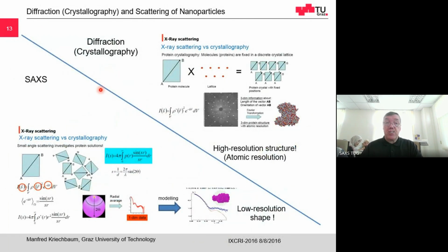So we go on. The difference between crystallography and SAXS. In single crystal X-ray diffraction, you have to take crystalline samples, so you have to get a crystal. And in a crystal, all molecules adopt the same configuration or the same position with respect to the X-ray beam. In that case, you don't get a diffuse scattering pattern, you get sharp diffraction points. And if you do the evaluation, you can get then the atomic structure, because you have the phase information and the intensity information. And by that, you can solve the atomic structure of your molecule, if it can be crystallized.